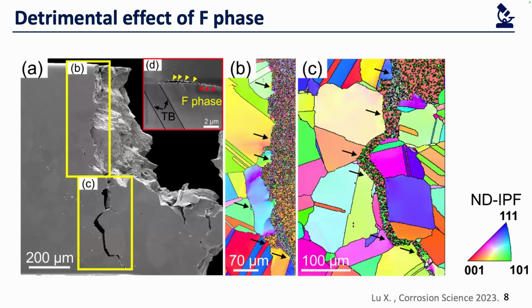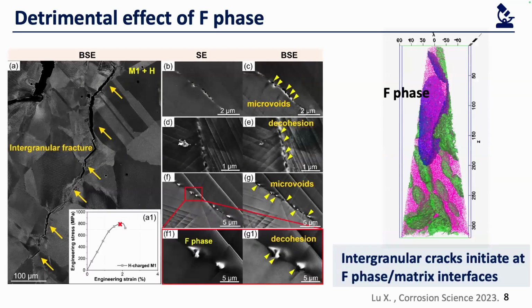Tensile testing results revealed the same behavior. So we can see these tiny phase precipitates along the grain boundary, and in the hydrogen environment, the interface between the phase and the matrix fractured, and nanovoids can be observed. As you can see also here from the EBSD results, we can see the total intergranular fracture of this material. In-depth analysis using tensile testing, with secondary electron images and BSE images, also reveals microvoids along the interface of this phase and the matrix. You can see this is the bad guy we are looking at.